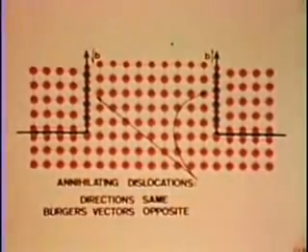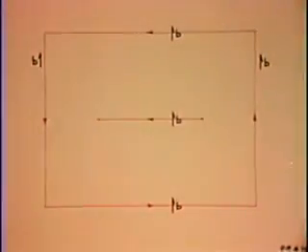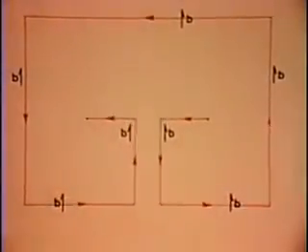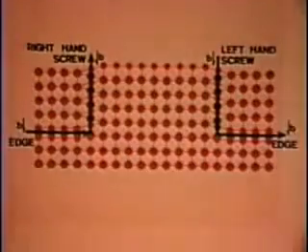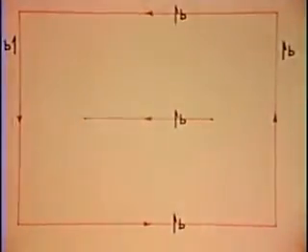When the two screw segments coincide, their atomic configurations disappear. The edge segments being trailed behind the colliding screw segments become two continuous dislocations, the upper becoming the original edge segment ready for another cycle, the lower completing the free loop which surrounds the slipped region.